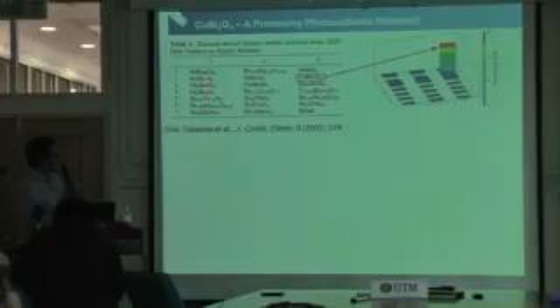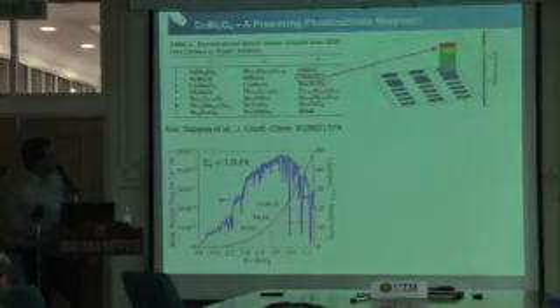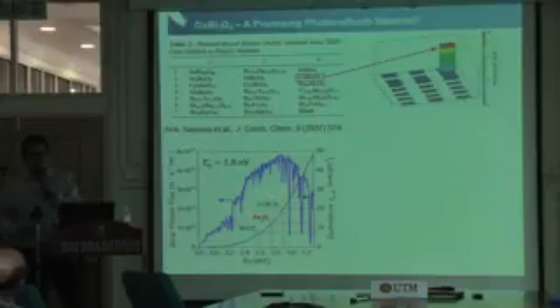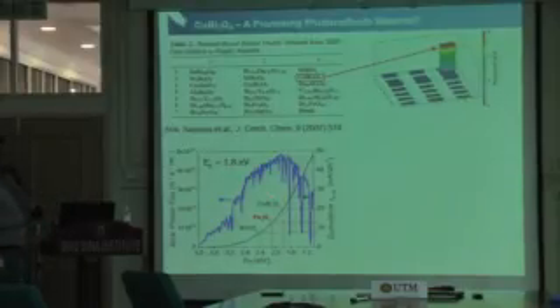So another one is copper bismuth oxides. This is actually one of the hit materials from a combinatorial study done in the group of Sayama. They tried to look at different bismuth oxides, and copper bismuth oxide is one of the hit materials here. If you take a look at the band gap, it's 1.8 electron volts, so it's really ideal. This is really what we're looking for.